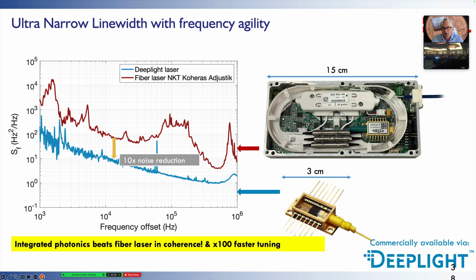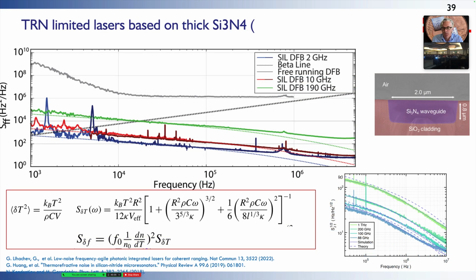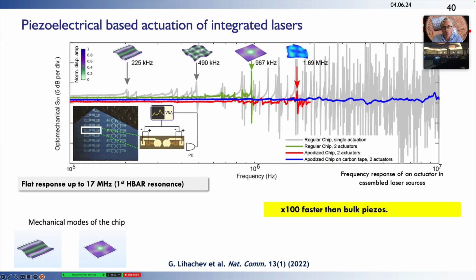But the importance is not just the linewidth. What we can achieve with the silicon nitride is, moreover, very, very fast actuation. What's shown here is the response to applying a voltage on the piezoelectric actuator that we sweep from 10 kilohertz to 10 megahertz. What you can see in gray is that if you have the device just on an optical table, in an optical assembly where the chip is not clamped down, the piezoelectric actuator is exciting many mechanical modes. These are the modes of the chip itself, the photonic integrated circuit, in this case 5 by 5 millimeters.